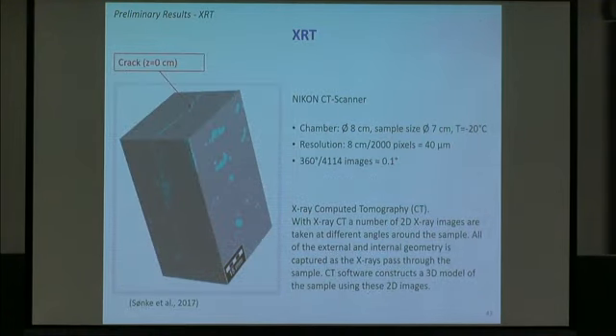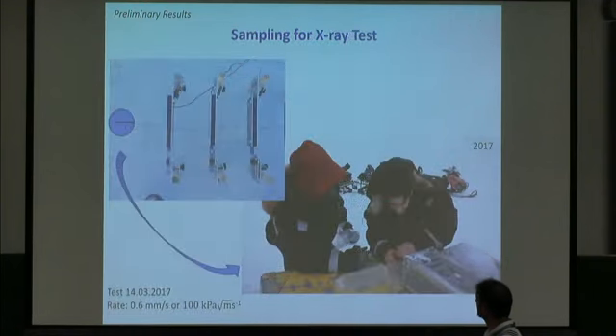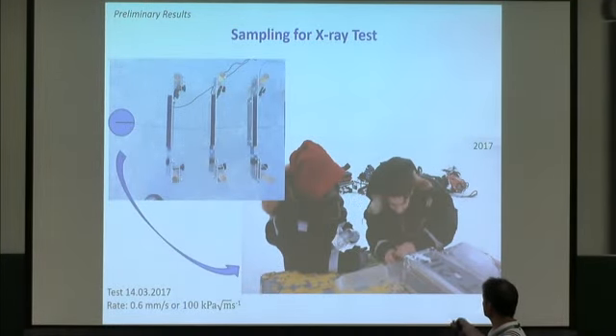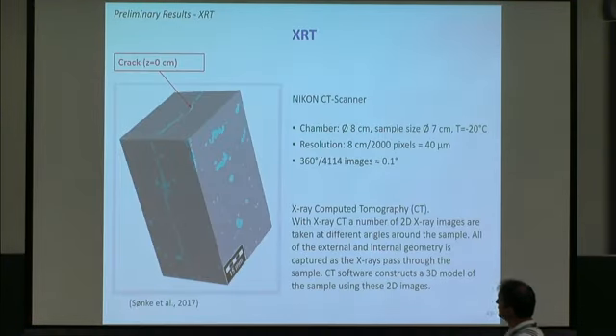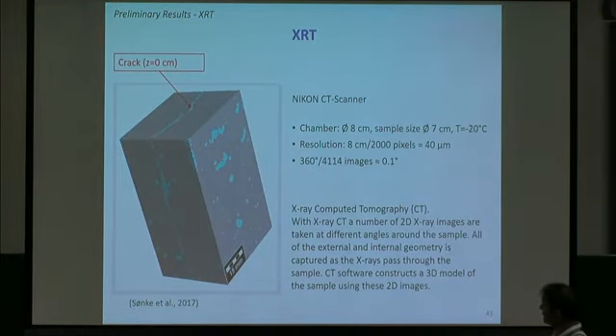So here, from the core you saw now, is an X-ray scan. I think that this is from the core you saw on the previous slide. That means from the very top here, which is behind this cage here, we have captured the crack, but this sample didn't capture the very tip for the one we ran X-ray on. But I will show thin sections where we have that in. So Z is equal to 0. That means we are on the surface.